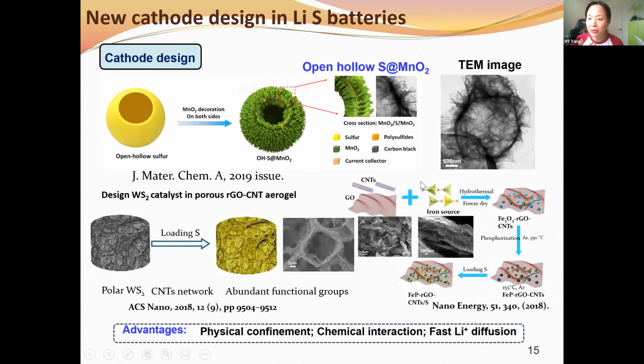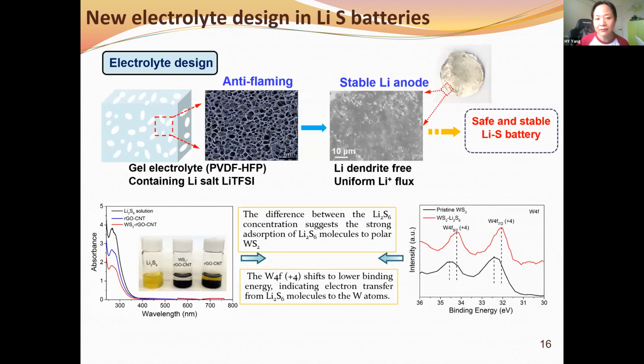So our research group has been focusing on all three methods to improve the current lithium sulfur battery. We have designed a cathode with a trapping system to keep the sulfur inside, with either carbon or manganese outside. That has a very positive impact, giving high stability for the lithium sulfur battery, and also a high surface area for chemical interaction and fast lithium ion diffusion. We have also focused on electrolyte design, which is anti-flaming and very stable. At the same time, we provide a very stable lithium anode with a protection layer, which will be very safe for implementing such lithium sulfur batteries in electrical vehicles.